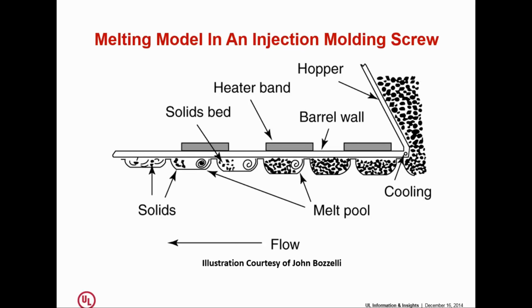And so what we typically will do is we'll raise the temperature of the material to try and get these last few pellets melted, which is kind of like taking a glass full of ice water and taking a propane torch to the glass in order to get the ice cubes melted. You will get them melted, but in the process you'll overheat the rest of the water. And that's not necessarily what we're trying to do. We're trying to get the whole glass of water to be the same temperature. And so this involves gentle distributive mixing.